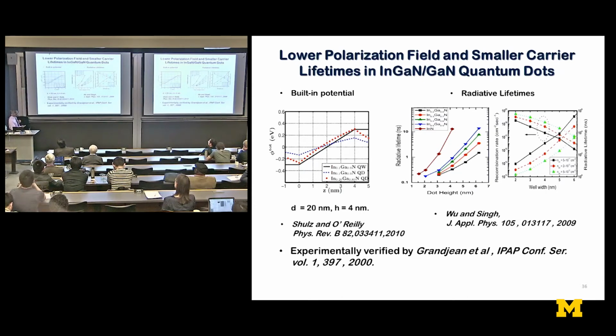And then Jaspreet Singh and his group here also calculated the overlap integrals and radiative lifetimes in these quantum dots and compared them with wells. And it's clear that the lifetimes in the quantum dots are at least 2 orders of magnitude smaller. And when I looked at these results, it was clear that this is the ideal. This is perhaps even a more important system than arsenides and phosphides to use quantum dots, because in addition to all the other things about quantum confinement and large gain and differential gain and all that, you have this additional advantage of a lower polarization field.